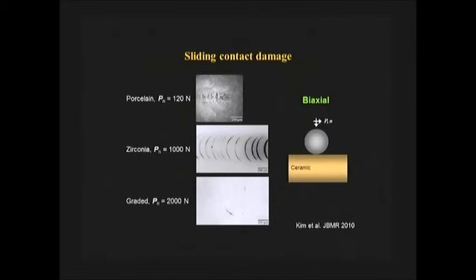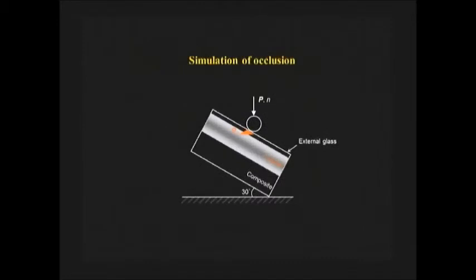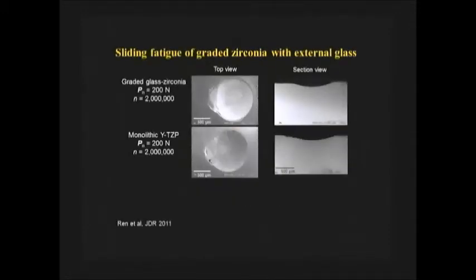And in case of graded structures, at 2,000 Newton, you only see some initiation of cracks on the surface. That's what we did with one sliding cycle. Now we also show you a cyclic fatigue test with this aesthetic surface glass layer, 20 micron thick, on graded structures. What we did was 200 Newton, 2 million cycles sliding on a surface.